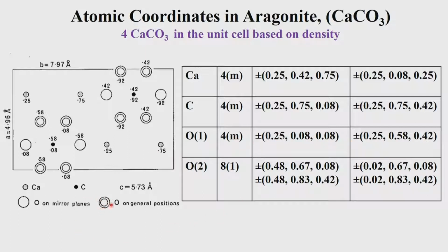You see that the oxygen positions are indicated in a bigger open circle which is shown up here. So, the carbon atoms came here. It so happens the 2 carbon atoms sit on top of each other. This is at 0.08 and 0.58, and the carbon atoms here therefore are half added to the Z value. So, they sit at 0.42 and 0.92, and these 2 values therefore, this is 0.92 is 1 minus 0.08, and this value is 1 minus 0.58. So, you see carbon atoms come up at these positions. So, the carbon is one above the other along the Z direction.